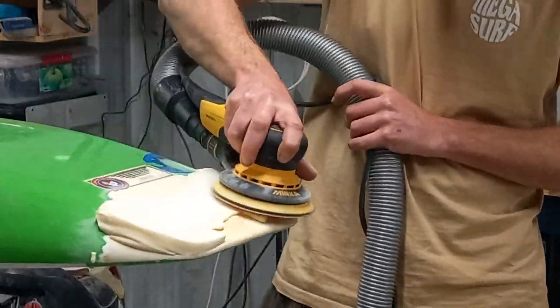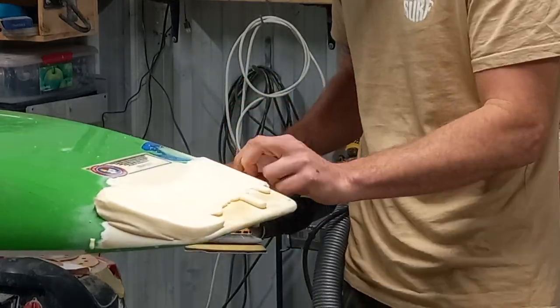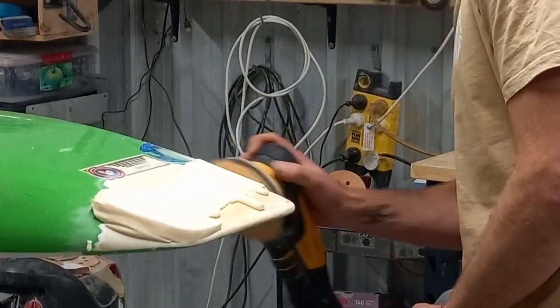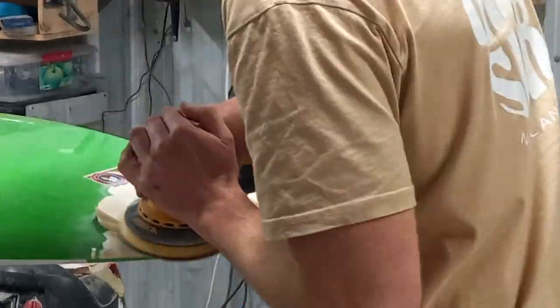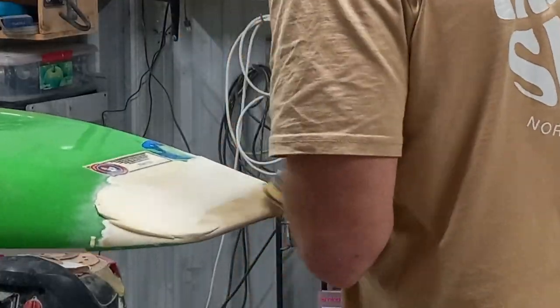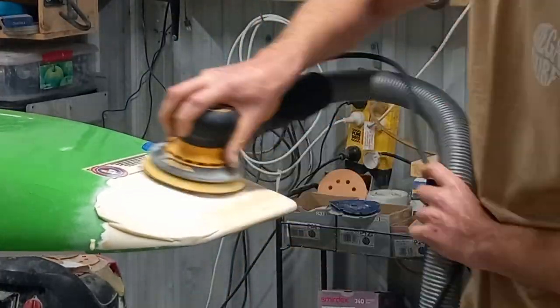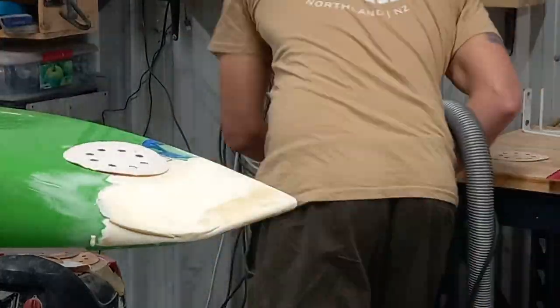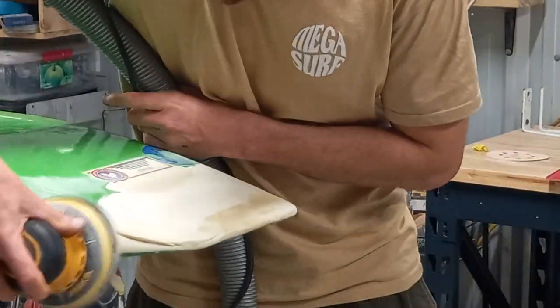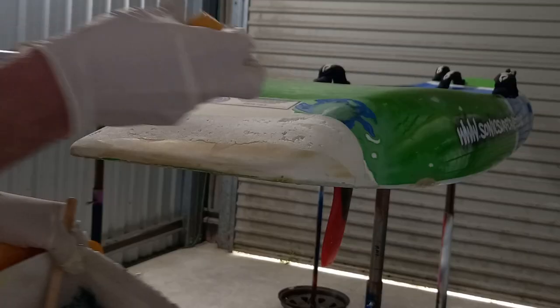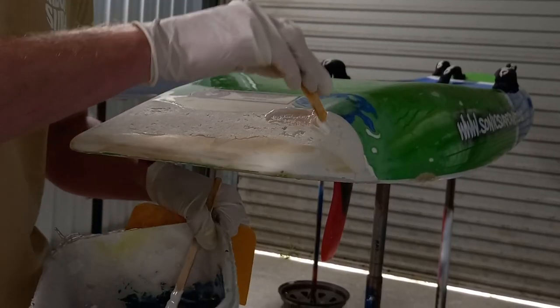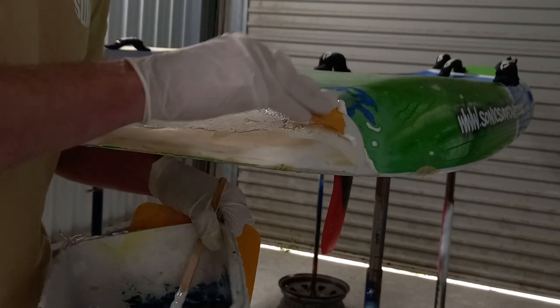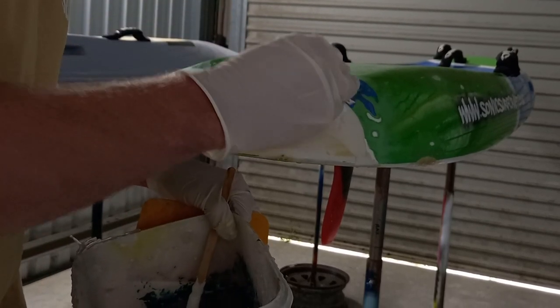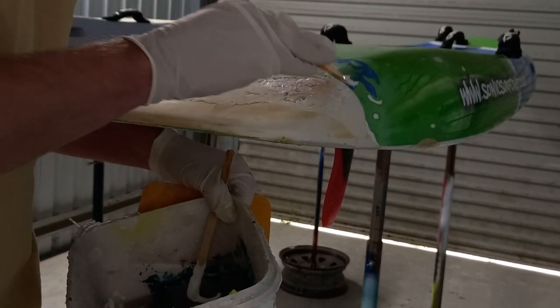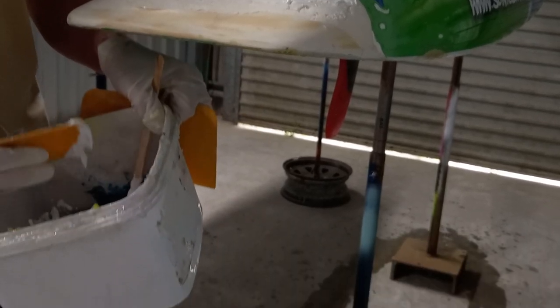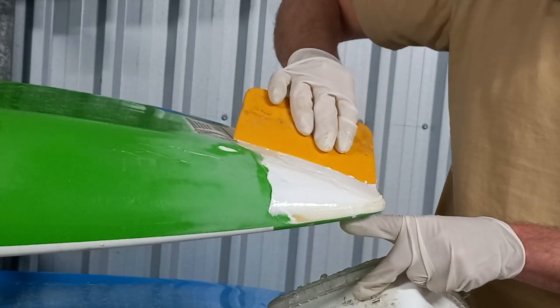With a pour of this size, there will inevitably be some air bubbles. I did fill the larger air bubbles that I could see with more foam, but there's always going to be some smaller ones. So that's where our next stage of filling in those air bubbles, giving it a skim with some resin and some micro balloons, comes in. Keep in mind that our foam is sanded pretty much perfectly to shape. So the real goal behind doing this is to force as much resin and micro balloon mixture as you can into any little air bubbles.